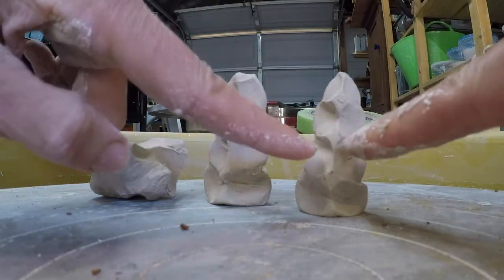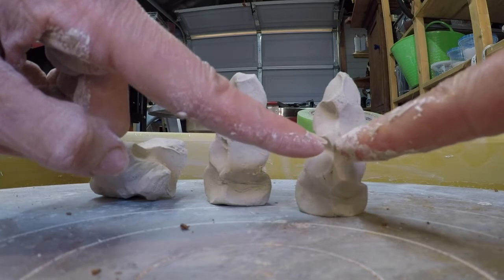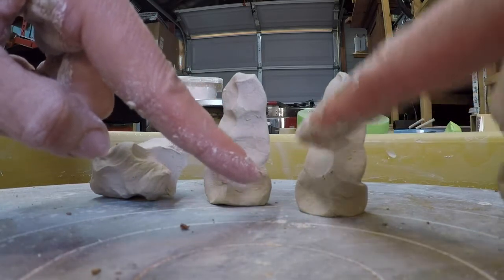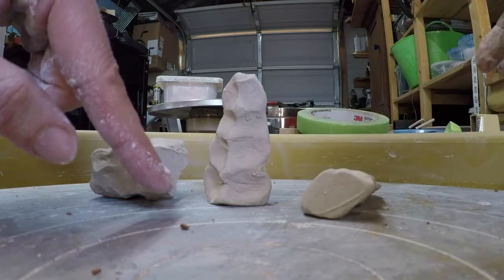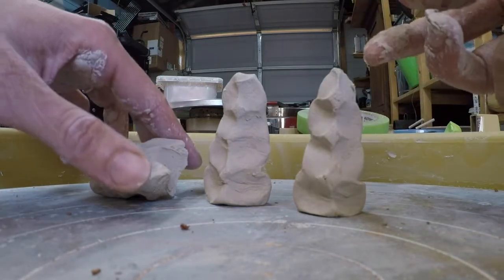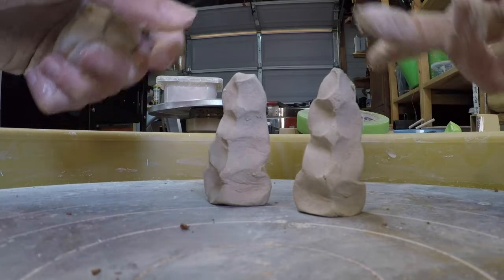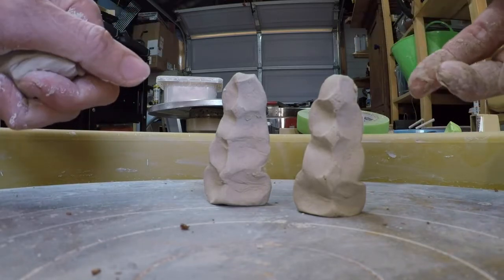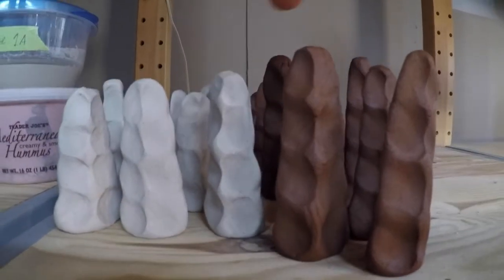And what's nice about this is on these high spots, you can see where the glaze is going to break, where it's maybe going to highlight a color, or where you're going to be able to see through to the clay. And then you'll have these pooling areas. And also you want to make sure your test tile is standing straight up. You don't want a test tile that you fire on the ground, because you won't get the same effect as you would for most of your stuff. The only flat things we fire generally are plates. Most of your stuff is going to be like a cup or a vase or something that's standing up. So this is going to give you the best understanding of the effect that you're going to get. Also make sure when you're doing your test tiles, do one white and one red.